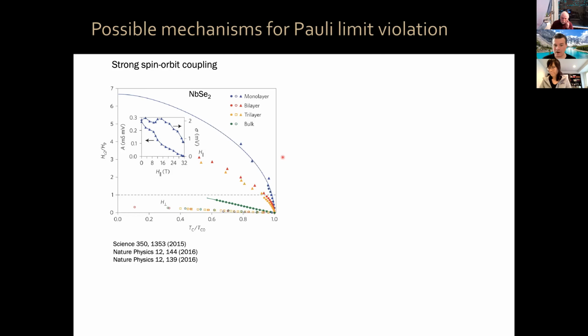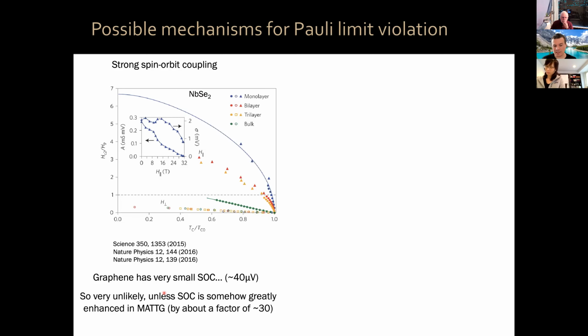However, graphene has an extremely small spin-orbit coupling, okay? Orders of magnitude smaller than these systems. So it is very unlikely that spin-orbit coupling will be able to explain our huge Pauli limit violation, okay? It would have to be about a factor of 30 larger than it is in graphene, in magic angle trilayer graphene, in order to begin to account for the Pauli limit violation ratios that we observe.